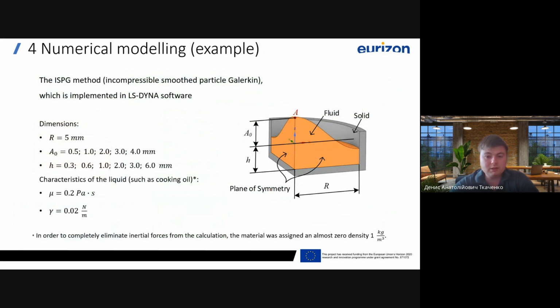To validate the analytical model, we compare it against numerical results obtained using the incompressible smoothed particle Galerkin method implemented in LS-DYNA. This is a meshless Lagrangian-based approach tailored for simulating viscous fluid with free surface, surface tension, and fluid structure interaction. In our simulations, 1/4 of the domain is modeled with radial size 5 millimeters, and Newtonian liquid with properties similar to cooking oil is used.